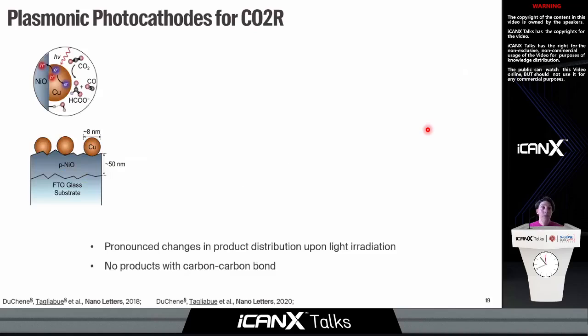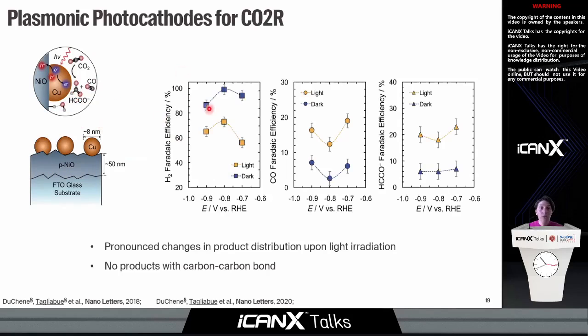We have more recently fabricated an analogous system where we have copper on p-type nickel oxide to maintain the Schottky barrier to a reasonable degree. And in this case, we have again performed the CO2 reduction process, and we have observed that 3 different products are generated. We always have hydrogen, we have carbon monoxide, and in this case, we also have formic acid. The blue dots are in dark, and the yellow dots are under illumination.